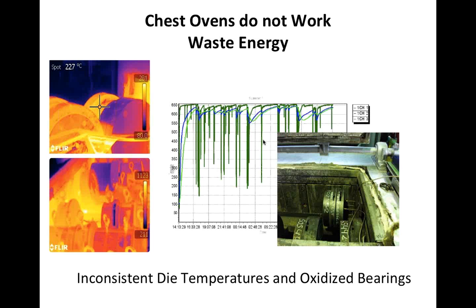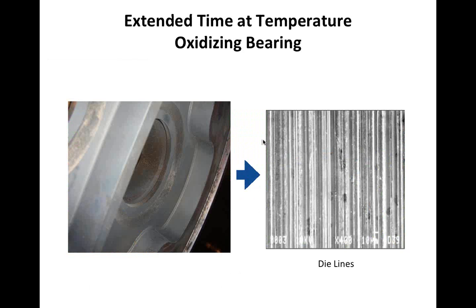Unfortunately, more than 50% of the global extruders today still use chest ovens. And the reality is, to heat a die in a chest oven, we have very little, if any, control over temperature. And the majority of these dies are left at temperature for too long, causing oxidation and surface finish problems. This is just a quick look at a die that's been in a die oven for more than 8 hours. And you can see through the microscope that it's caused oxidation on the die bearing and die lines on the profile.